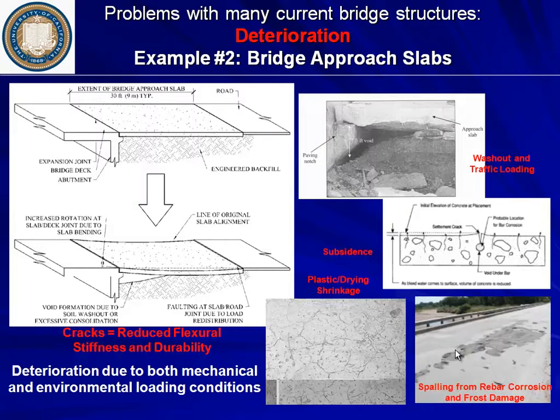Next example is bridge approach slabs. In this case, it's the same issue. You have a very strong deterioration, and the deterioration is caused by both, again, mechanical loading and environmental loading. Mechanical loading just because of the truck loading. You have deflection because of the soil washout, which is a big problem. And you have, of course, fatigue damage, but you also have all the environmental damage associated with it. Here you have all the rebar corrosion, frost action, subsidence cracking, drying shrinkage cracks, and so on. So the deterioration is a combination of both environmental and mechanical conditions.